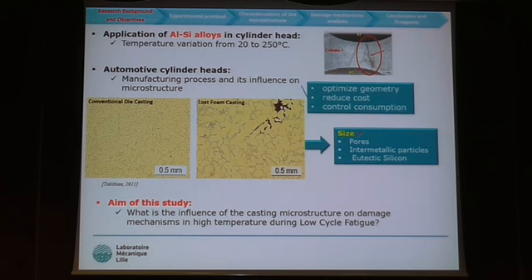And recently, the manufacturing process had changed from the conventional die casting to the lost foam casting in order to optimize geometry, reduce cost, and control consumption. But this change has a main disadvantage, which is the microstructure. As you can see here, the microstructure is coarser with more defects. The size of the different phases inside the material increased. So the aim of this study is to understand the influence of the casting microstructure on damage mechanisms in high temperature and during low cycle fatigue.